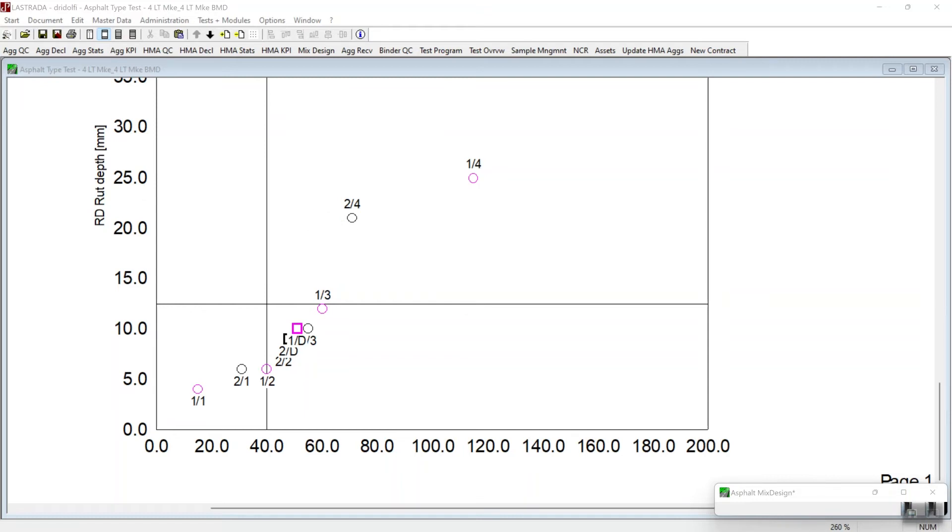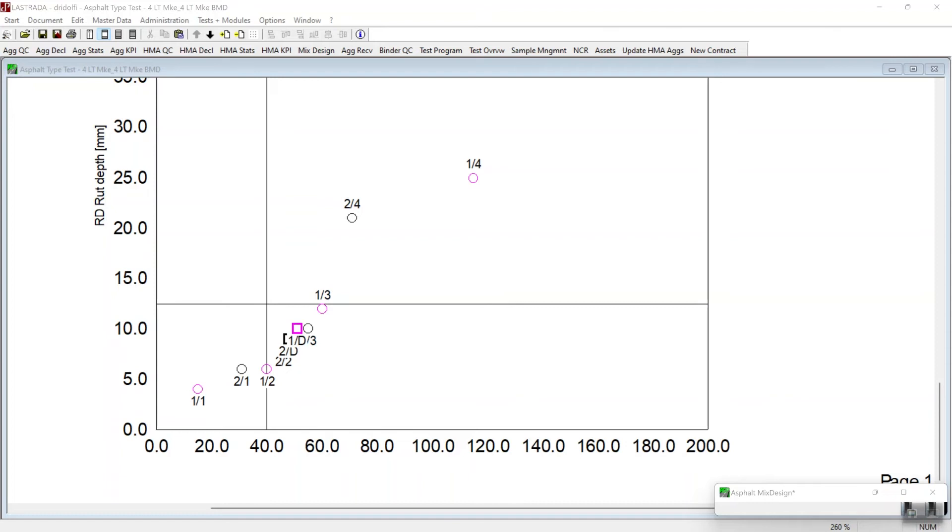Trial blend one, trial mix three is a really common occurrence with balanced mix designs. In this case, we see the ideal CT minimum has been satisfied, but we're very close to the edge of the maximum Hamburg rut test result. And we need to ask ourselves, can we maintain this balance? And it's a pretty easy question. We just look down a data point and up a data point to ask ourselves, can we maintain the balance? And if I look up into the right to trial blend one, trial mix four, we're significantly out of spec with the Hamburg wheel tracking test. So the answer is probably not, but let's look at the tabular data to confirm that.